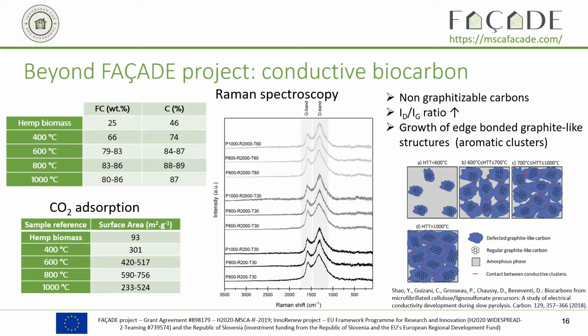Even if biocarbon is a non-graphitizable carbon, when we increased the temperature, we were seeing the ratio of the D band on the G band increasing, which meant that we get a growth of edge-bonded graphite-like structure. And these aromatic clusters are closer and closer to each other, so in good correlation with the microporosity that was decreasing at 1000 degrees, allowed an increased contact between the conductive clusters, and that's why we got the higher conductivity at 1000 degrees.